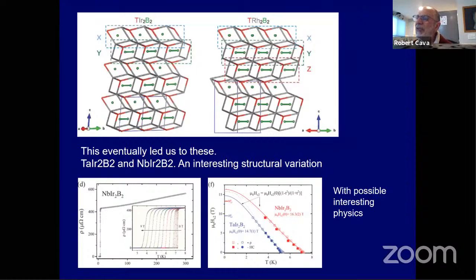minor bizarre characteristics. And until we can grow crystals of them, which is a very annoying thing, of a big enough size, physicists are not going to be able to study them to show that they're really interesting. But they do have a clue that there's something bizarre about them because their upper critical fields at T = 0 exceed the Pauli limit. So the Pauli limit is something that says if you apply enough field on a superconductor, you should break up the pairs, the superconducting pairs. And if you apply more than that, then you have something exotic.